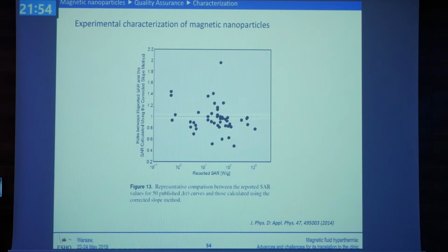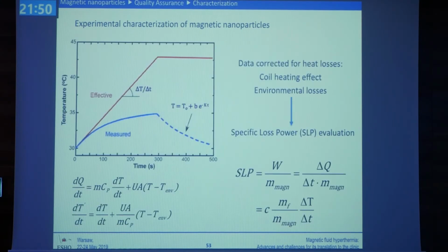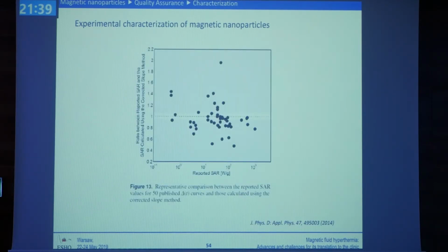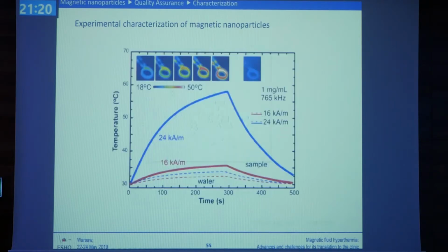And you can see that here. This is a very interesting paper where they took what was measured in the literature from 50 different nanoparticle systems, and they corrected for the adiabatic system, and you can see that the range of the reported values relative to the actual SAR after the correction can be up to a factor of 2 or a half. This means that we have 100% uncertainty in the measurement of the SLP in some of the systems that are around in laboratories all over the world. So what we do is we always do the heating and the cooling, and of course we also do the heating and the cooling for the solvent alone without the nanoparticles, because this also gives us information on the energy that is transferred from the coil to your sample.